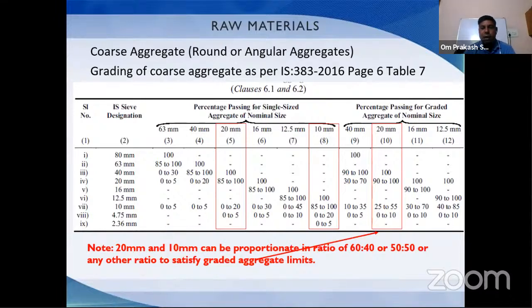We have to check the aggregate, mix them, and check the sieve analysis, and one more thing we have to do: take a density bucket, and besides the proportion like 60-40, also try 55-45, 50-50. Mix both aggregates, fill the density bucket, and check the weight of the aggregate. The proportion which is giving the highest weight is most likely to be suitable for the concrete mix design. Okay.